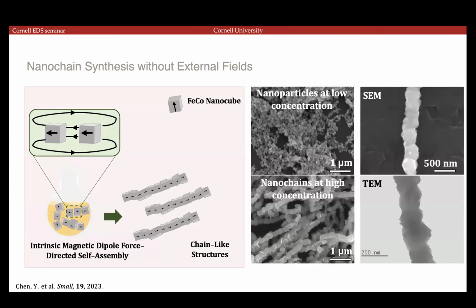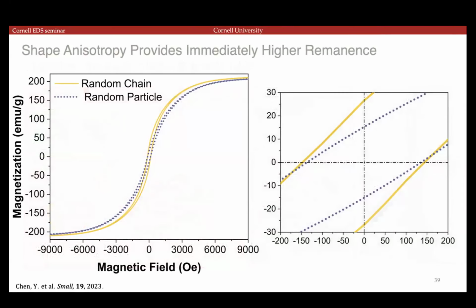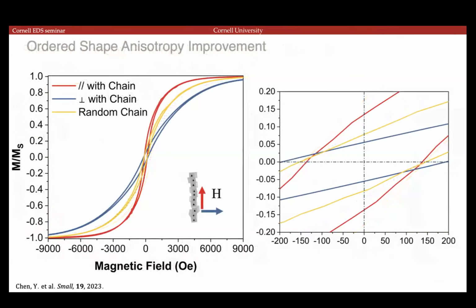So these are not chains that, once you remove the field, will break apart again. They're pretty much growing onto each other. And these ended up giving us the best performance so far. If you just compare the random orientation of the particles versus nanochains, we already see an improvement in the remnant magnetization for the nanochains.